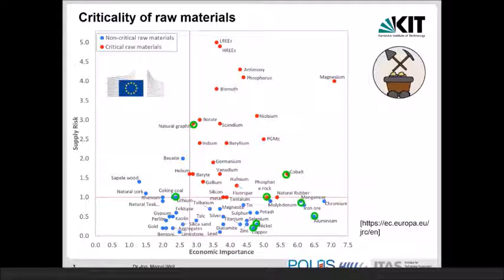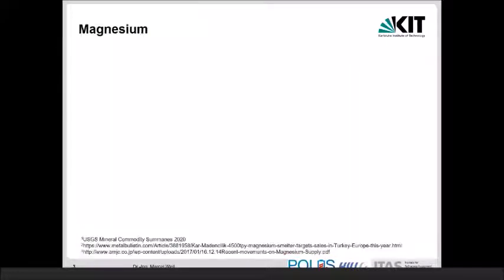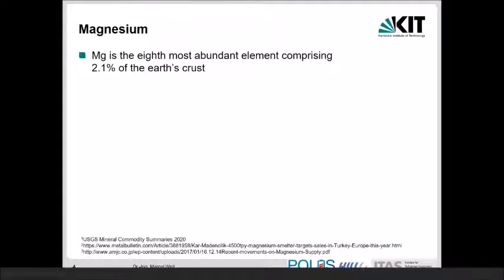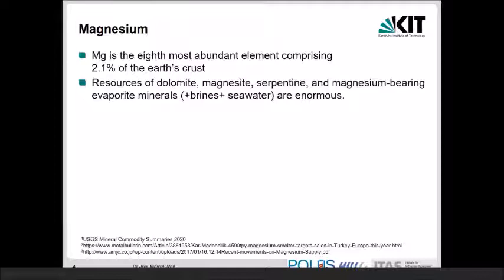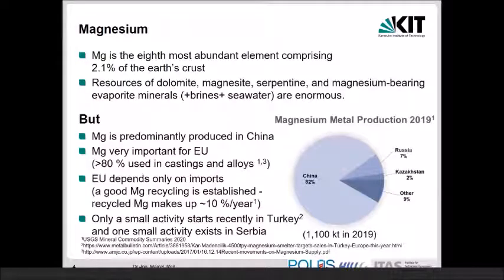But now the magnesium batteries. If you look at the criticality of magnesium, it's really above everything. From an EU perspective, magnesium is one of the most critical raw materials, and that's a little bit astonishing, as also mentioned several times already. Magnesium is the 8th most abundant element in the Earth's crust. The resources are dolomite, magnesite, serpentine, a lot of magnesium evaporites, brines, even seawater, and they are really enormous. So there is not really a big shortage, and availability should not be a big issue. But the problem is that magnesium is predominantly produced in China. So they more or less take over the market.